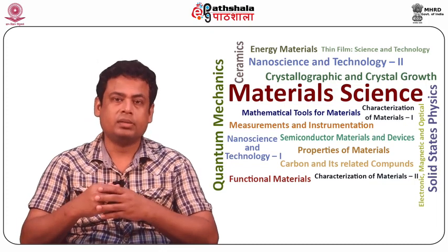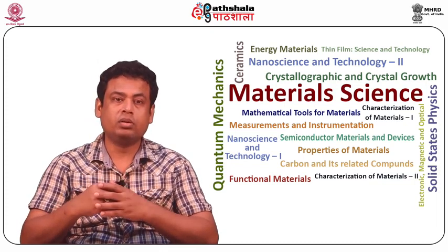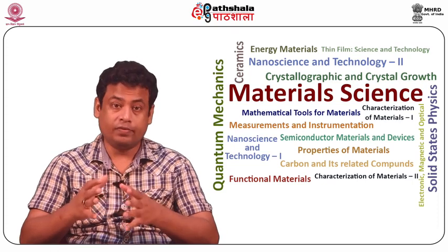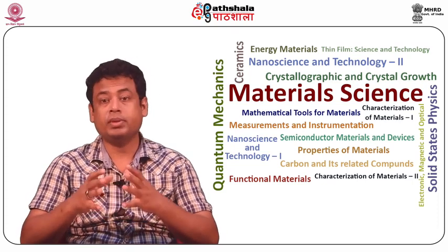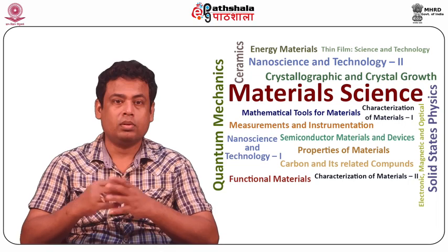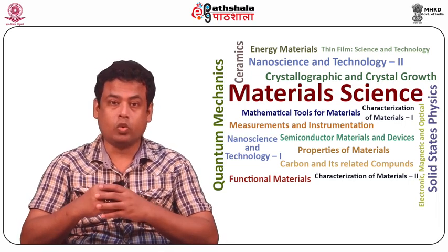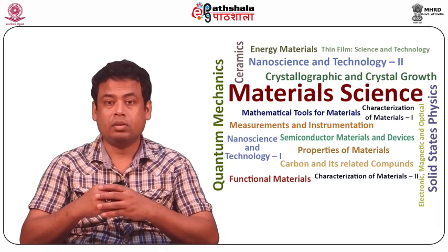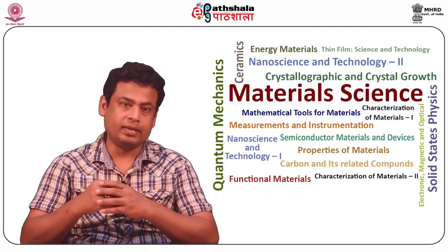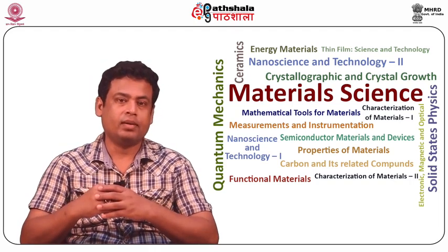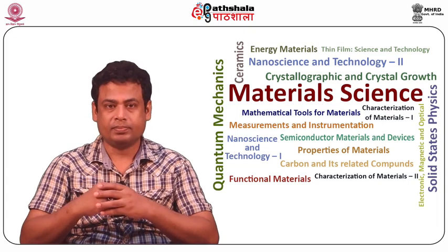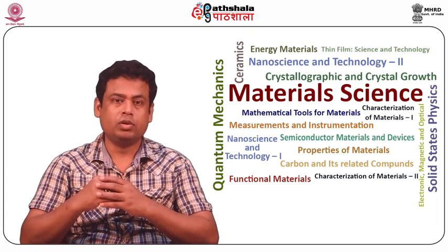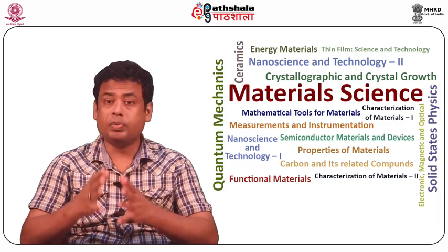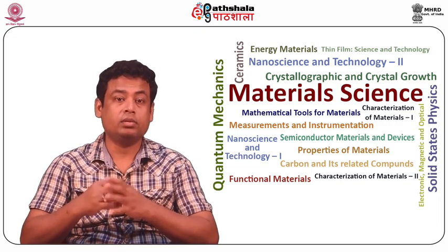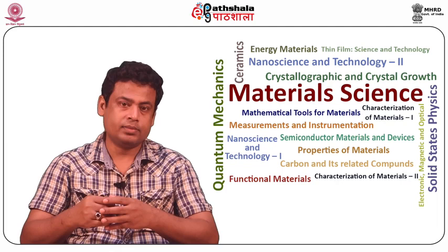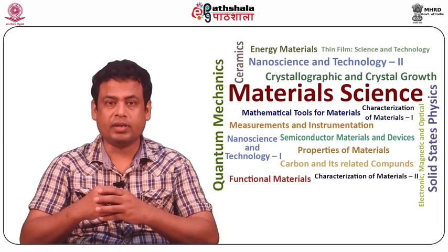Several phenomena such as adsorption, desorption, surface segregation from the bulk, measurement of diffusion coefficient and catalytic activity of surfaces can be investigated. It is used to study the compositional changes on the surface of alloys during ion sputtering.